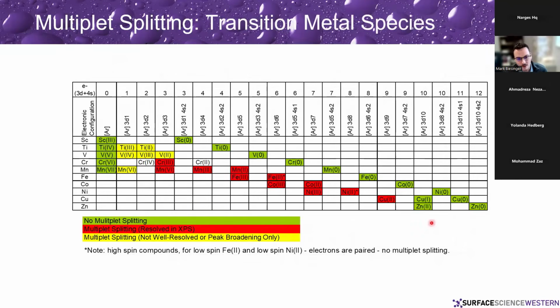If we look across the first row transition metals, and we look at all the species that can show this multiplet structure, the ones in red will have strong multiplet structure very present. The stuff in green are either the metals or do not have unpaired electrons, and so they will not show any multiplet structure. The ones in yellow technically do show multiplet structure, but it's not well resolved, so sometimes it just shows up as a broadened peak.